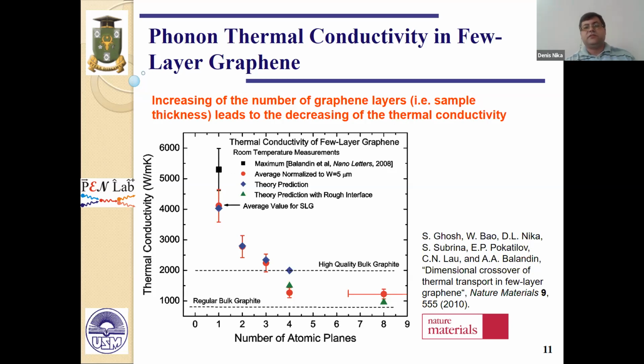Few layer graphene also demonstrates unusual dependence of thermal conductivity on the number of graphene layers. In conventional semiconductor films, thermal conductivity usually increases when we increase the thickness of the film, because in this case we decrease the boundary scattering of phonons. But in single layer graphene and few layer graphene, thermal conductivity decreases with increasing number of layers and approaches the bulk graphite limit at approximately 8 monoatomic layers.